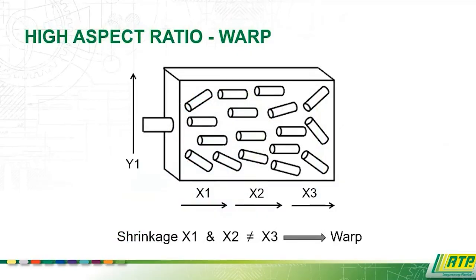First, we were talking earlier about those high aspect ratio fillers, good for reinforcement, things like glass fiber. That's great, but one of the downsides is they actually tend to introduce warp. Anybody familiar with working with glass fiber reinforced products has probably run into it. So what's actually happening there is when the material is injected into a part, those fibers or whatever filler we're using that has any aspect ratio want to align in the flow direction. And what happens there is the shrink in the flow direction is reduced more than the shrink in the cross flow. So we have a differential in shrink. And when there's that differential in shrink, we get warp. See potato chipping, it's commonly referred to, and just a lot of problems that come up with that.